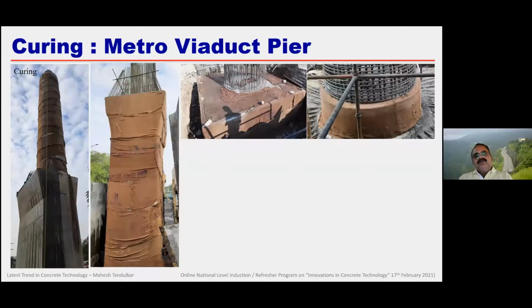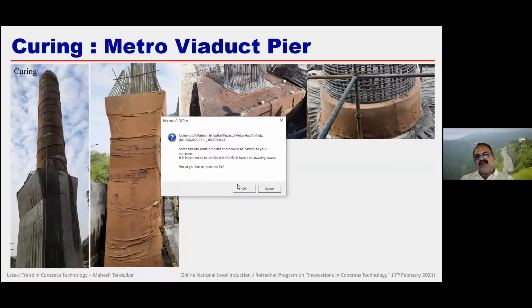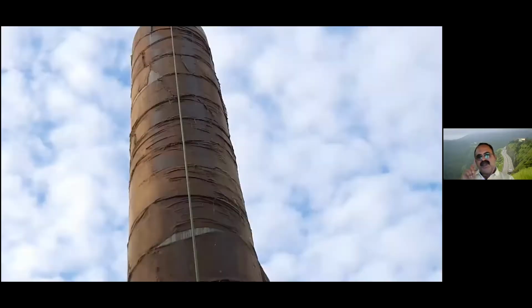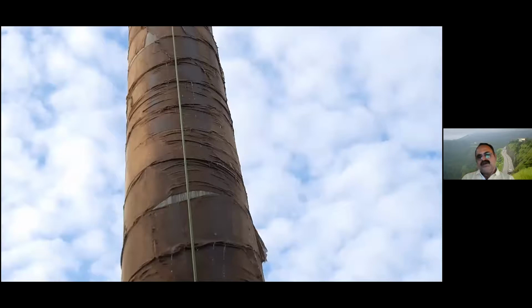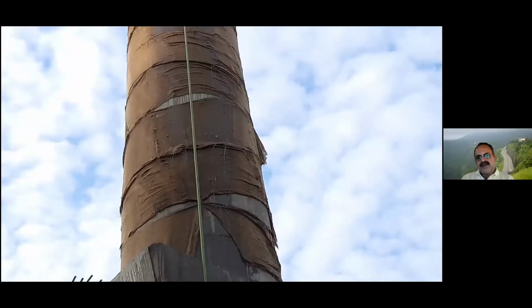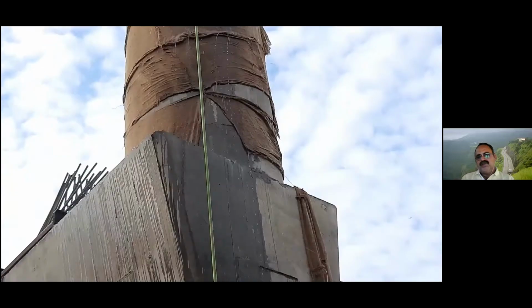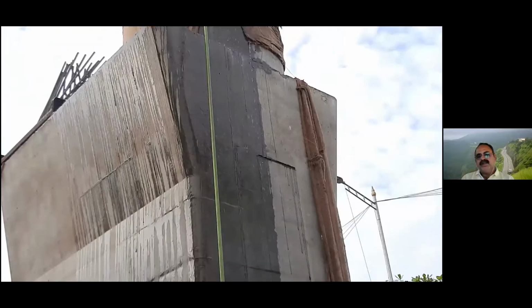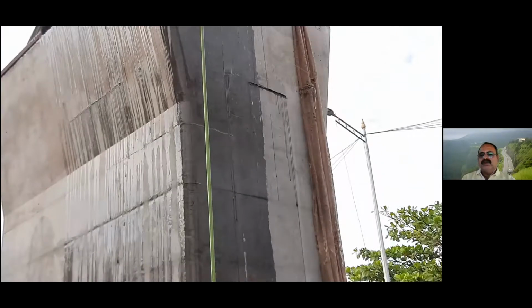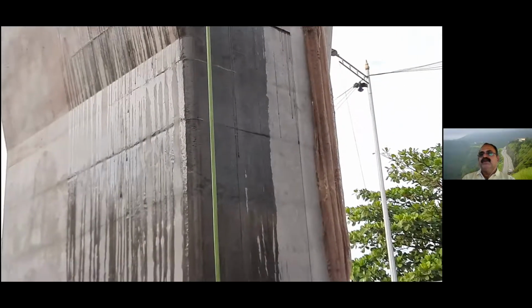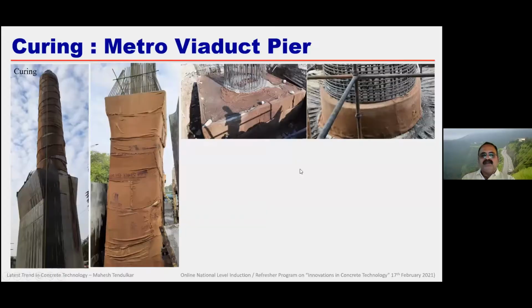Even in Mumbai, you must have visited and seen this. All metro piers, viaduct piers, are properly cured, some about 20 meters in height. You can't imagine curing such a high pier by normal water spray. A simple water pipe is laid on the top, connected to the water tank and a pump at the bottom, and it can cure the concrete for 14 days or 7 days as per the required time. So this is how effective systems can be made once we desire. See, there should be a desire to do good work, then it can be done.